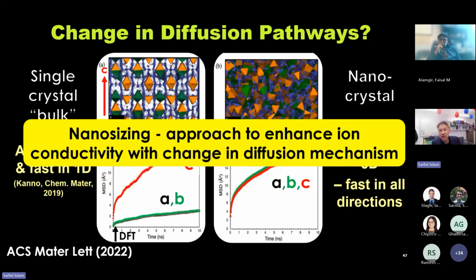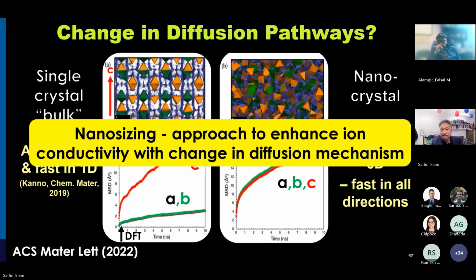So this is the conclusion. The nanosizing enhances lithium-ion conductivity with a change in local structure, but also a change in the diffusion mechanism. So that's quite a nice prediction. And I recognise that there are some challenges of going down to the nanoscale.